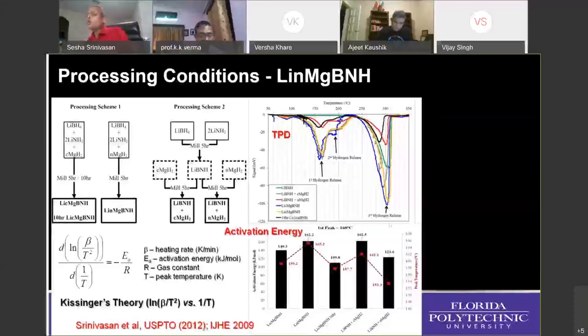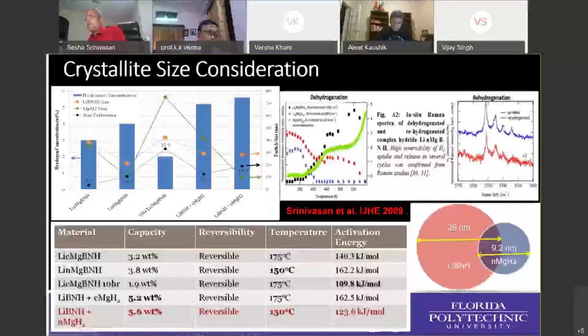So our goal was to decrease the activation energy of the materials. We tried to shop around five different processes, and then the one process we chose gave the lower activation energy. Again, this is a little detail. You also look into temperature programmed desorption to see the hydrogen desorption over the different types of mechanisms. I wanted to point out how X-ray diffraction is very useful in quantifying any results.